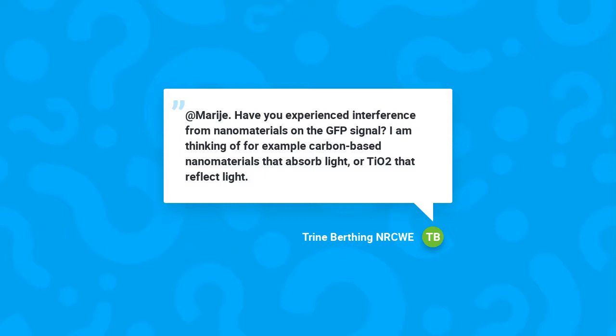Yeah, that's indeed a good question. So we have tested up to 100 micrograms per milliliter, and there we saw indeed with the highest concentrations that there's so much saturation of these nanomaterials that it will interfere with your GFP signal. But it was primarily for the highest concentration that we tested.